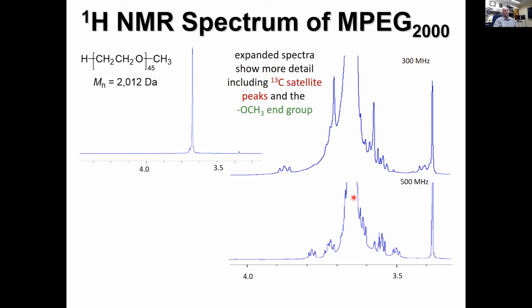Normally, this peak that I've got the laser pointer on is going to be an area of about 180 if it was really a 45 mer polymer, and this would be 3. I can integrate 180 to 3 sort of well, but it's still a pretty big number to a small number. If this were 450, that is if the polymer were 10 times larger, this would be 1800 to 3. 1800 to 3, I can't really integrate. That's like measuring the weight of a flea by taking an elephant that has 10 fleas, cleaning it, and then weighing it again. You're going to get lousy numbers.